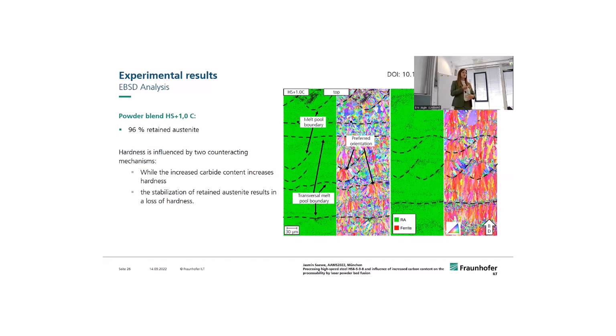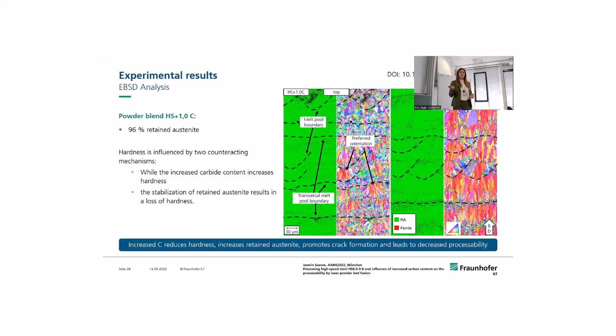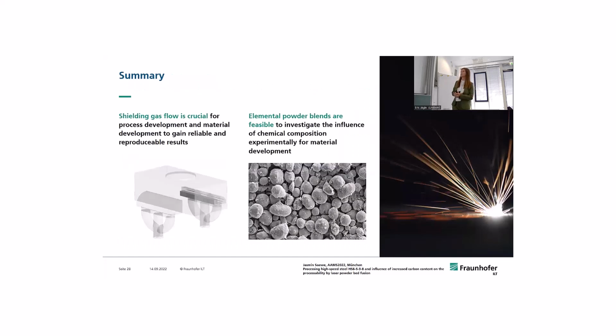But if you think about post-processing or the whole process chain with heat treatment, then it might even be possible to increase the hardness compared to the reference. In the end, and that's where the conclusion and summary comes up, for us it was interesting: elemental powder blend works, retained austenite is not the key, and it's interesting to use the elemental powder blends in LPBF for investigating new materials.